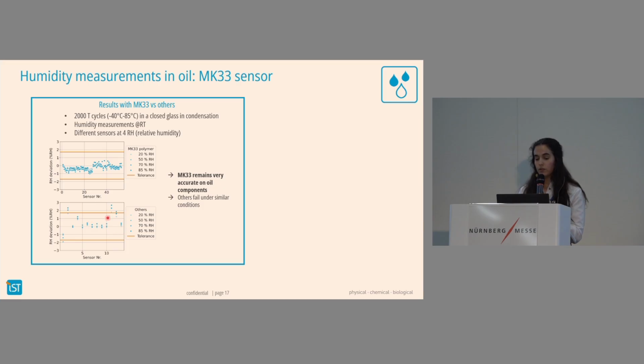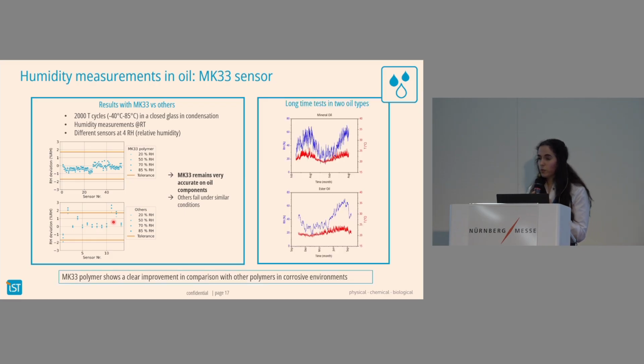So while others' accuracy comes outside of the tolerance range, the MK33 stays on range for many more samples than the others. And the final test that we did with this type of sensors was a very long time test in oil, so in a relatively corrosive media. What you see here is the humidity response against time, which is over a year, for 2 different types of oils. And as you can see, first, it's remarkable that it's working during this long period of time. And second, it's quite reliable and quite constant.